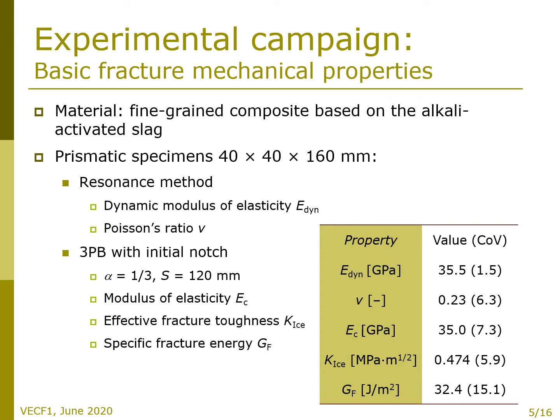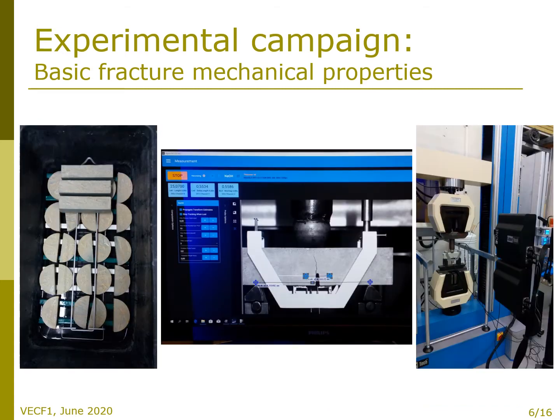To be able to use this material in praxis, its fracture mechanical behavior must be investigated and well known. You can see several details of the experimental setup, as well as values of Young's modulus, Poisson's ratio, modulus of elasticity, effective fracture toughness, and specific fracture energy obtained on defined specimens. In this figure, you can see the concrete specimens and the laboratory testing.